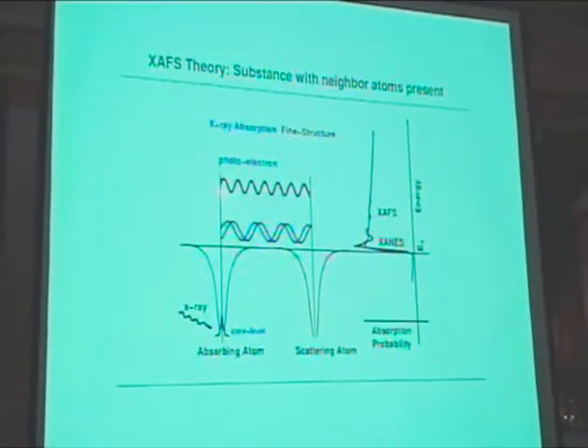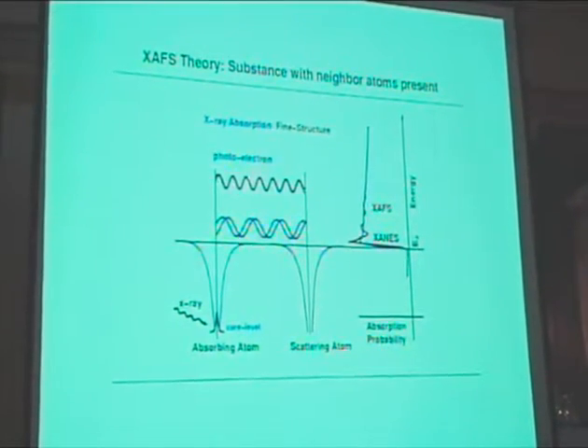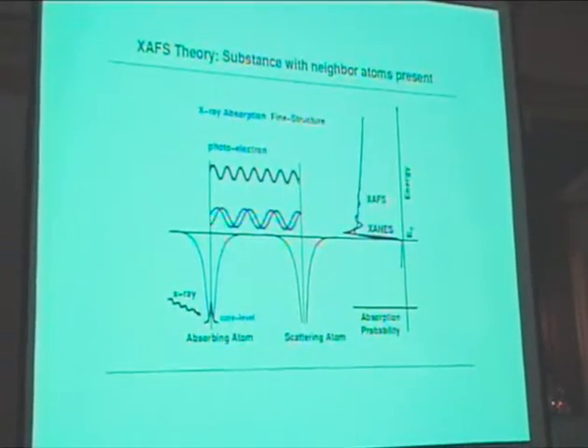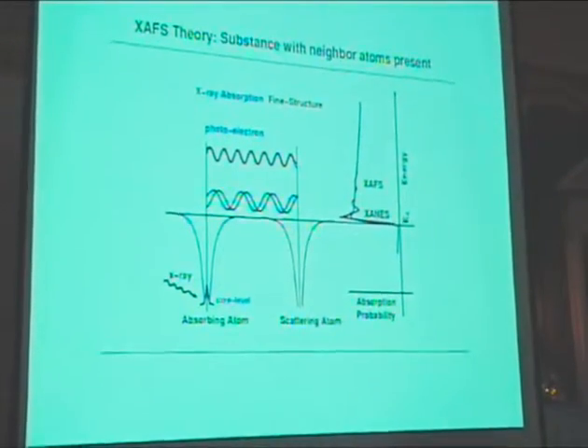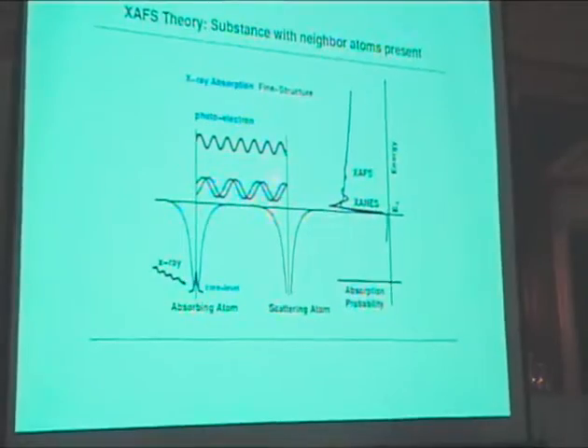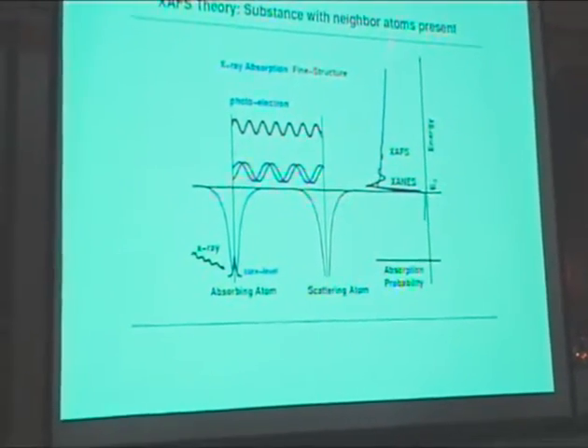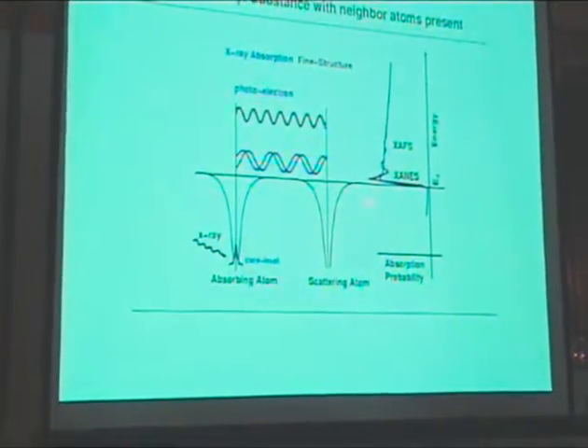And you can see several peaks every time you get a so-called resonance effect. But it's just a small fraction of the total number of electrons going out. So the majority is still in this structureless background. So what we must do is take away the structureless background, because that doesn't contain any information. And then we are left with those electrons which just do this resonance, those peaks here. And these peaks are because we are having this scattering effect.